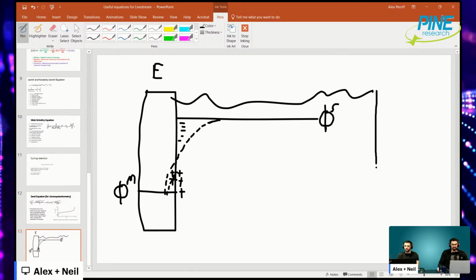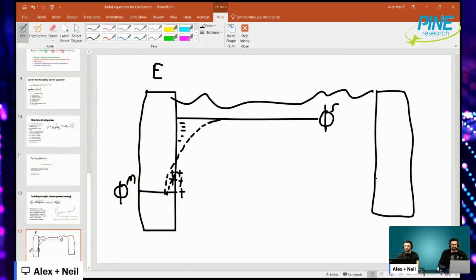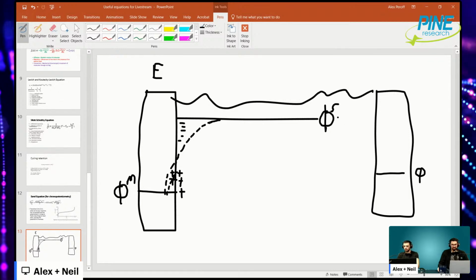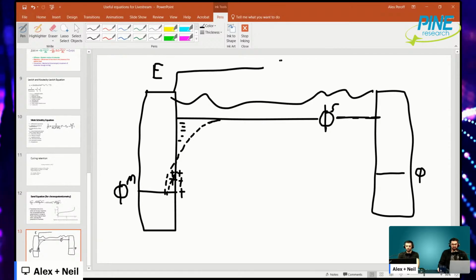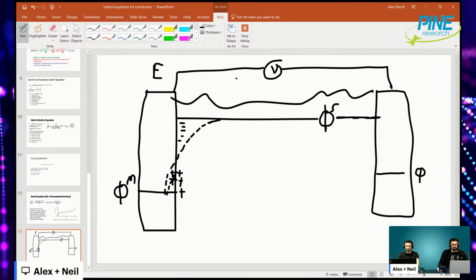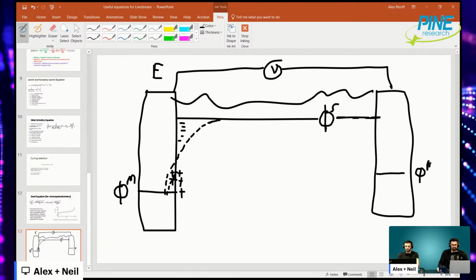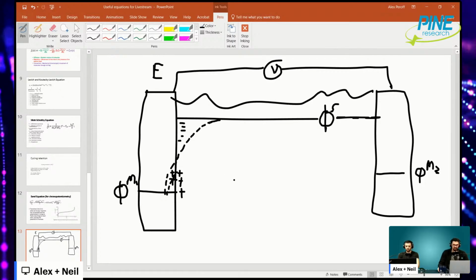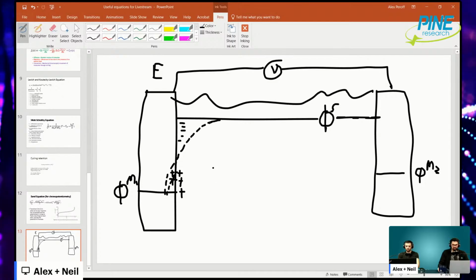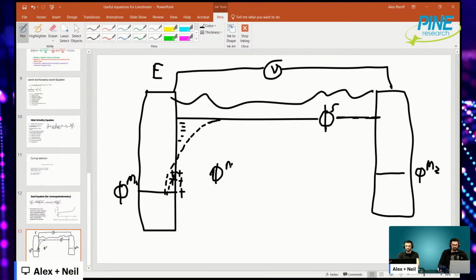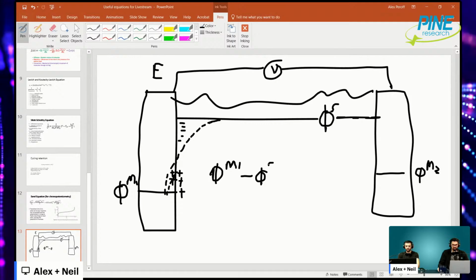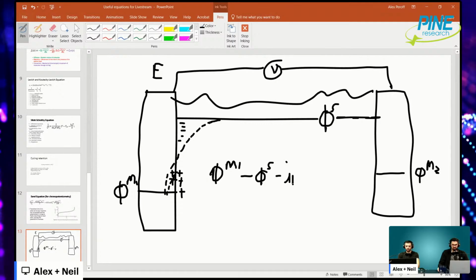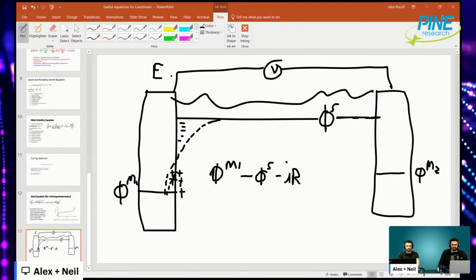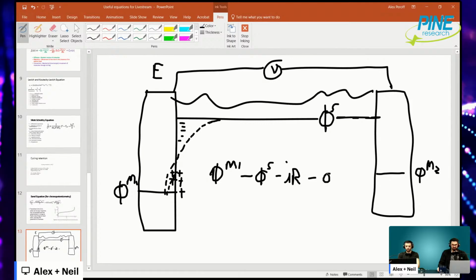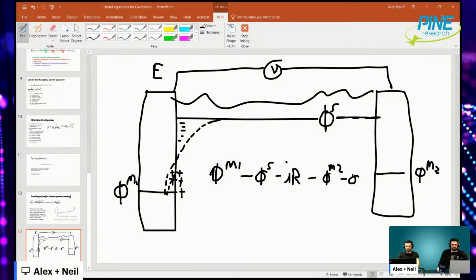And when you have another electrode in solution or in your system, it also has a phi, and it also has an S, so to say. And when you measure the voltage between these two, because this is what we can measure experimentally, I'm just going to call this M2, I'll call this M1, and the solution potential, let's say it's the same. What you are measuring at your voltmeter is phi M1 minus the solution potential minus the IR contribution, which is very small. It's very negligible, but you need a small amount of current with an IR drop to make this measurement, minus phi M2 minus phi S.